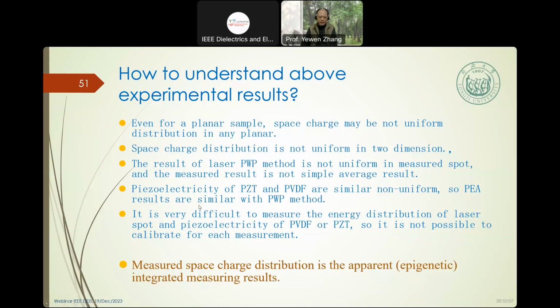So the PEA method is similar to the PWP method. It's very difficult to measure the energy distribution for the laser spot, and the piezoelectricity of the PVDF and the PZT. So it's not possible to calibrate for each measurement. So measuring space charge is an apparent, integrated measurement.